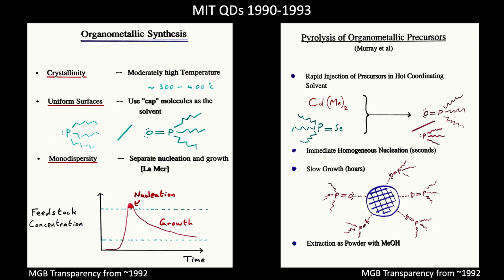So crystallinity is great. Uniform surface is great. Monodispersity from the nucleation and growth. Organometallic precursors, no water. And slow growth, we can extract with methanol and redisperse in all sorts of solvents and begin to process them like if they were very large molecules.